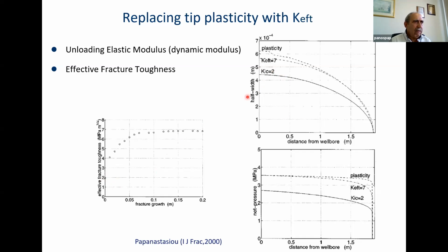The initial fracture toughness before propagation, the elastic fracture toughness, I will say, was 2. And this was the prediction by the elastic model. If we use the effective fracture toughness, the limit value, the pressure profile is this one here, as you can see. No, actually, this is not the pressure profile. This is the fracture opening.